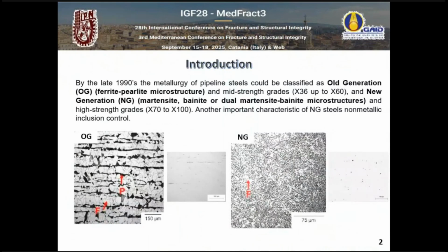Okay, let's talk a little bit of history. In the 1970s, with the development of the Trans-Alaskan pipeline, which required high strength but low carbon and low alloy steel to be able to build a pipeline that had to endure temperatures below minus 50 degrees Celsius and have high weldability and high strength, a new generation of pipeline steels appeared. These steels gradually have been replacing the traditional ferrite and pearlite steels with typical elongated manganese sulfide non-metallic inclusions.